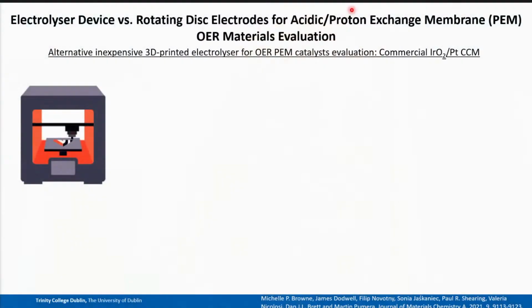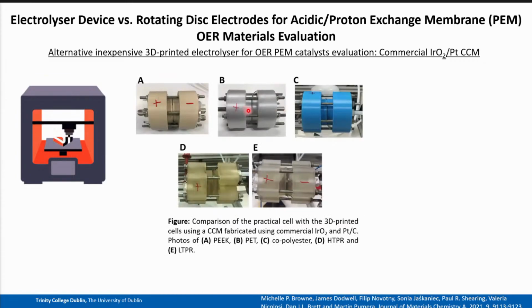So this is just my last slide. So to try and overcome this, I used some of my previous knowledge on 3D printing to try and make 3D printed electrolyzers to evaluate our OER catalysts under electrolyzer conditions in our labs. So to do this, we essentially use 2 different cheap 3D printing techniques called fused deposition modeling and stereolithography. So if you can see, these are B, C, D, and E are the electrolyzers that we 3D printed. And A is the standard practical electrolyzer cell